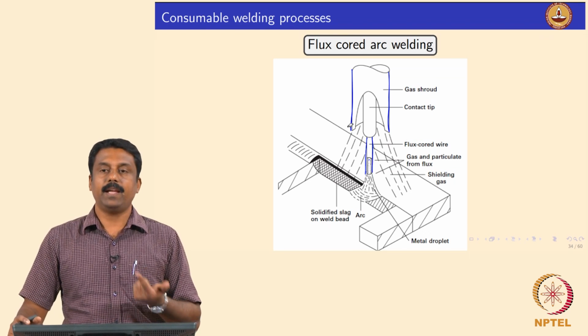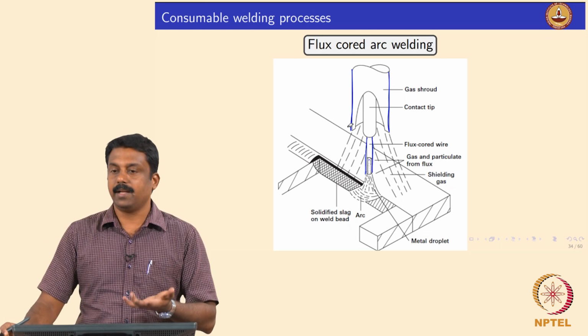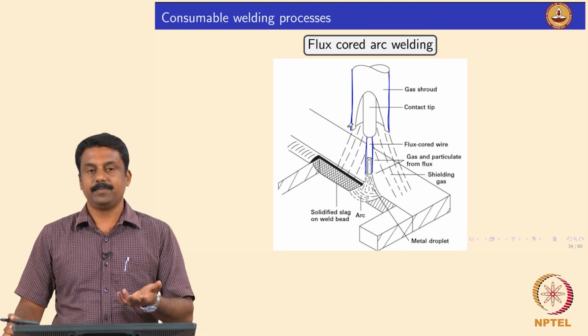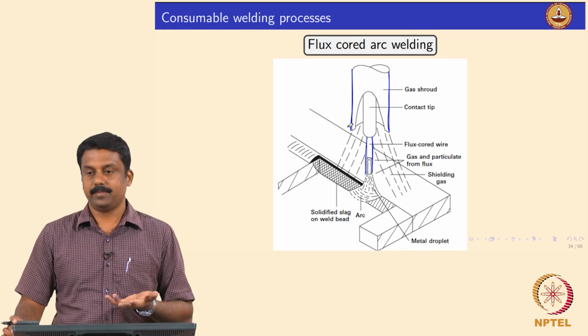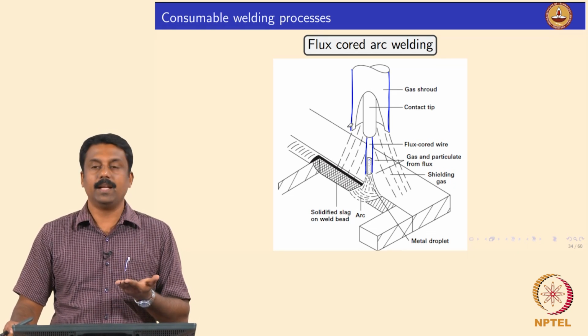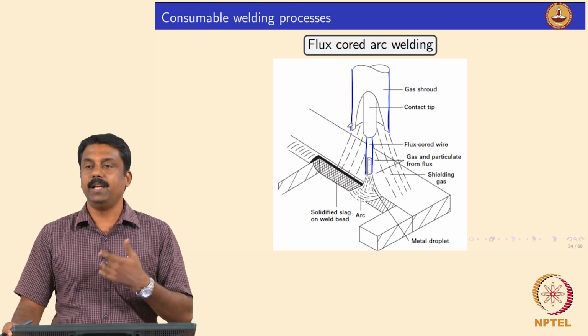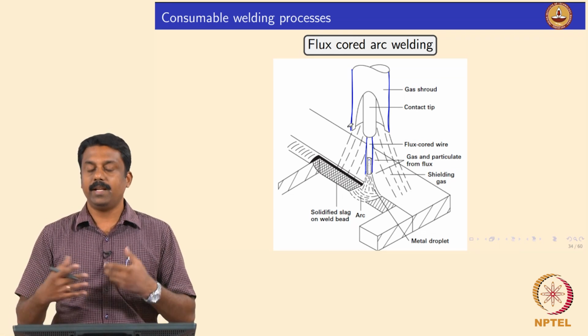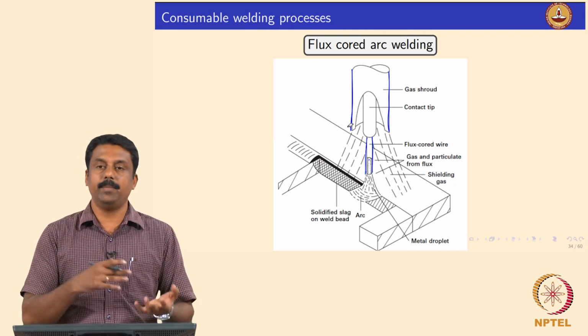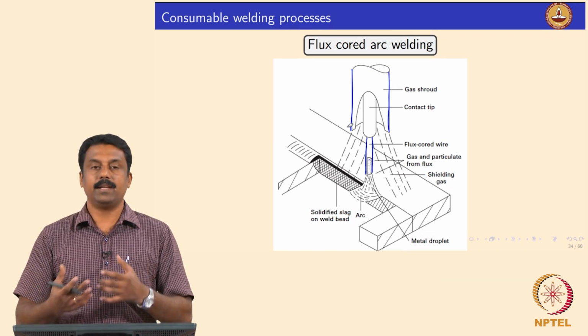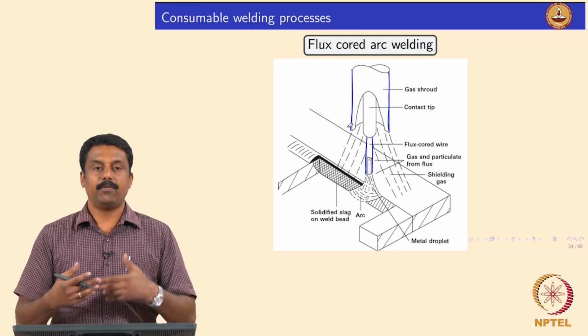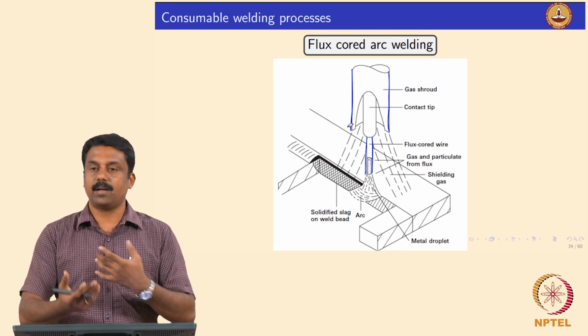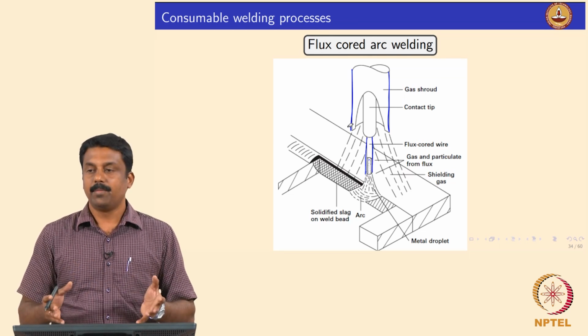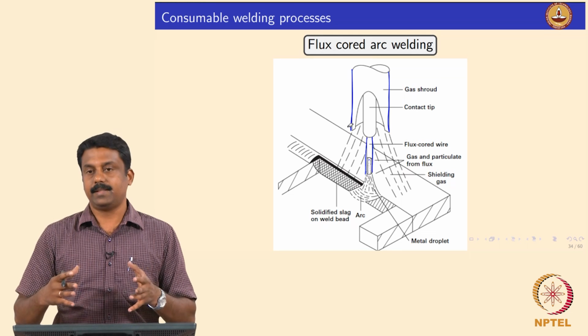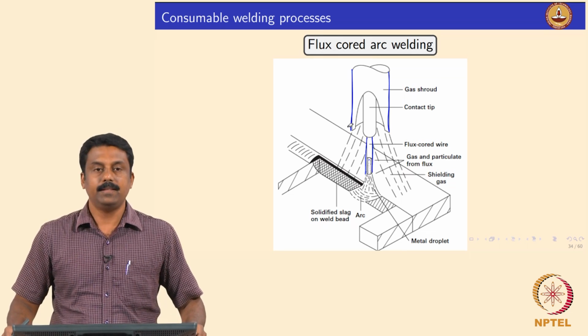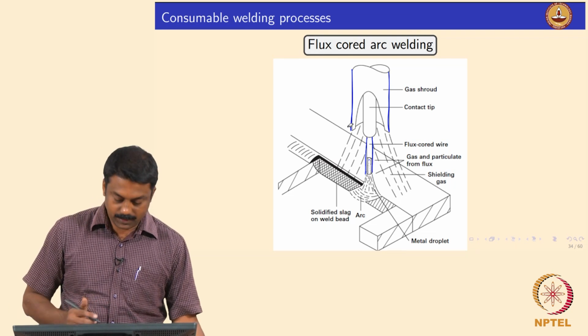Okay. So, in that case you can reduce the gas generating compounds from the flux, you can add more amount of alloying elements. Okay. So, in that case your process stability increases, it is similar to GMAW. The advantage is you get the efficiency of GMAW, and you also have the advantage of FCAW by having flux, the flux interfering with the droplet transfer, enhancing the kinetics of droplet transfer, also protecting the weld pool by the flux, the slag. Yes, it is clear. Okay, we will see one by one when we go further.